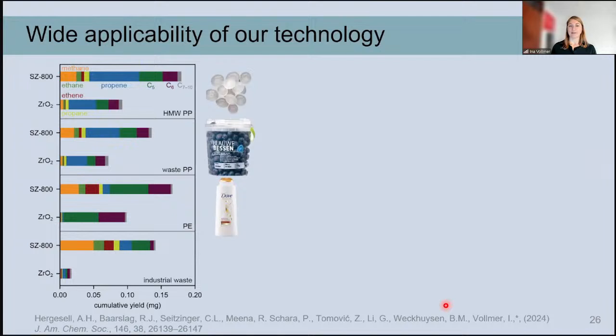Okay, so with that, a question that we often get is, so what is this process actually applicable to? So we have tried high molecular weight polypropylene and low molecular weight polypropylene. We've tried a waste item of polypropylene from this blueberry cup, and we've also tried polyethylene, and even this industrial waste, which also contains contamination of other polymers, so polyamides, PET, EVOH, and polystyrene. And in all these cases, you can see that these grinding spheres, which were catalytically activated, show a much improved performance over the commercial zirconia grinding spheres. And this is particularly striking for this industrial waste sample.